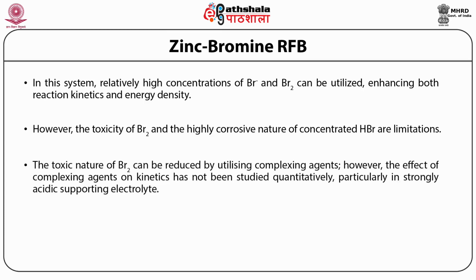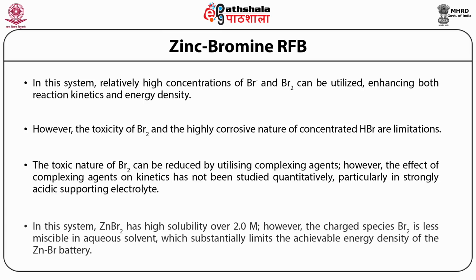The toxic nature of Br2 can be reduced by utilizing complexing agents. However, the effect of complexing agents on kinetics has not been studied quantitatively, particularly in strongly acidic supporting electrolyte. In this system, ZnBr2 has high solubility, over 2 molar. However, the charged species bromine, that is Br2, is less miscible in aqueous solvent, which substantially limits the achievable energy density of the zinc-bromine battery.